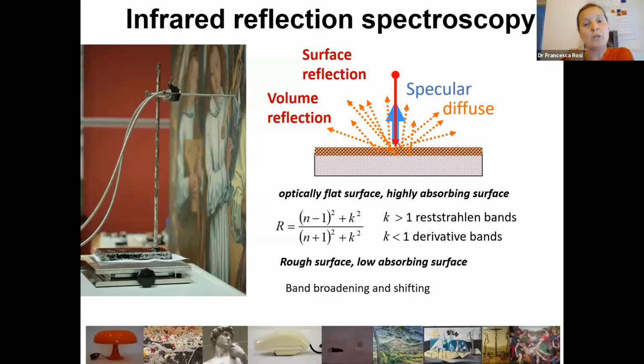As a matter of fact, when we work in infrared external reflection spectroscopy, depending on the degree of penetration of the incident beam, we may have both surface reflection and volume reflection if the beam reaches the inner layer. Both types of reflection generate spectral distortion, with surface reflection generating a larger distortion, like the crystalline bands, as we saw before for calcite, and for most of the inorganic oxyanions, like sulfate, phosphate, and so on.